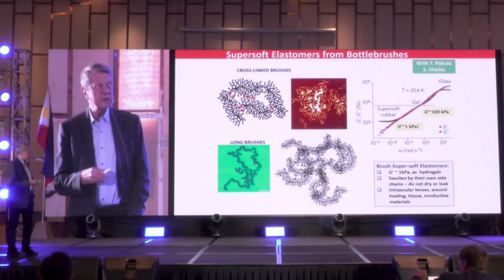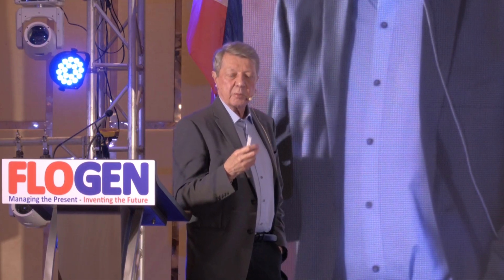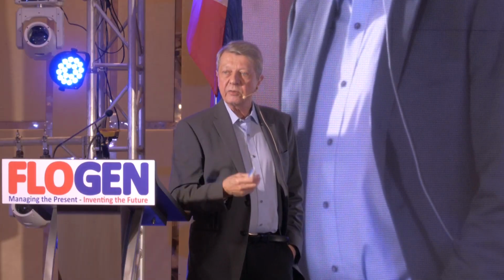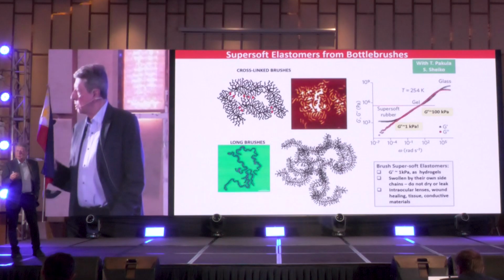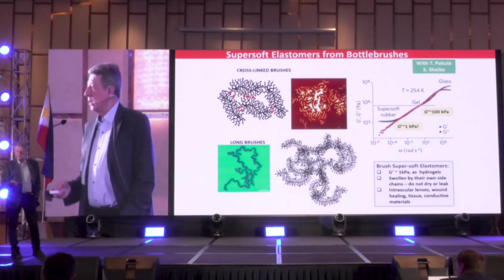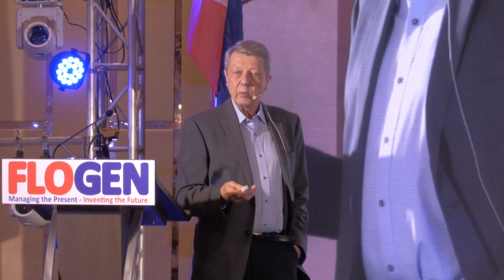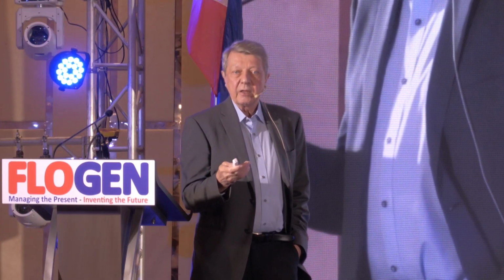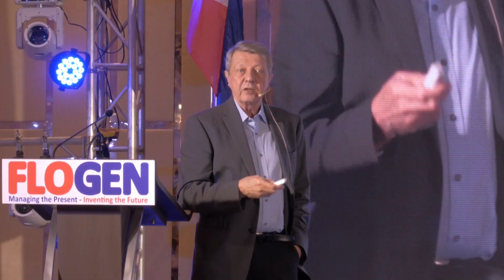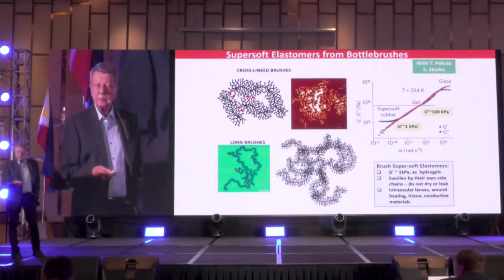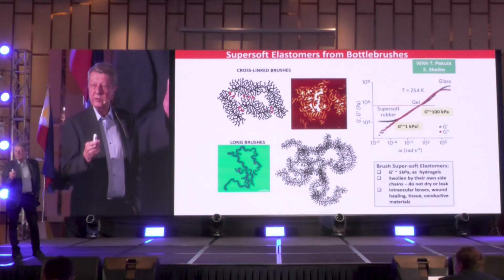But our bottle brushes are very short. They cannot entangle, so they relax further on, and they reach super soft rubber properties. So they are 100 times softer than rubber. So when you think, what materials do you know which are 100 times softer than rubber? Not many. So this would be something like a jelly or hydrogel. But hydrogel is 99% water, 1% polymer. When water evaporates, hydrogel becomes very hard. So that's why you cannot use them in contact lenses or any other applications, because they would hurt you unless you keep this lubricant like water constantly there. So can we make a material as soft as hydrogel, but which would never evaporate? A material which would be always super soft. So we tried to make them, and let's go to the next slide.